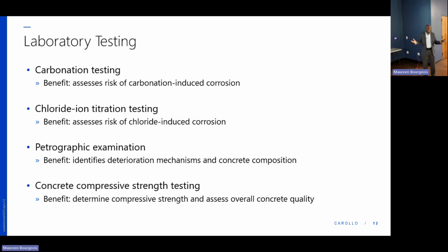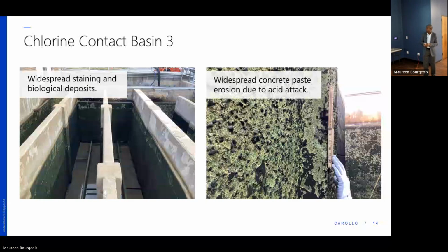Additionally, though, there are some bacteria that thrive in that environment. And whilst they thrive in there, they produce acids, and these acids attack the concrete because they're trying to break the concrete down. And so we see that widespread erosion of the concrete paste, which is that first surface layer of the concrete, being eaten away by some of these bacteria. Additionally, because the bacteria is so active in this environment, it also begins to attack not just concrete, but other elements of the structure.